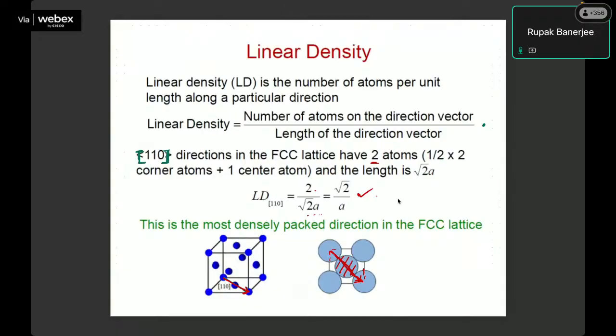Similar for linear density. Here it is rather easy to say, you look at the number of atoms in the direction vector divided by the length of the direction vector. For instance, if you are still looking at the 110 direction, which is this one, you see the vector is cutting through 1, 2, 3. So there is contribution happening half from two corner atoms and one which is coming from the center atom. Remember, this is a line, so the other atoms don't really count. I am only counting through a particular line. So they are contributing half for these two and one full. So you have two, and the distance is of course also root 2a, because it is the diagonal of a square, and hence your linear density of 110 is also root 2 by a, right?